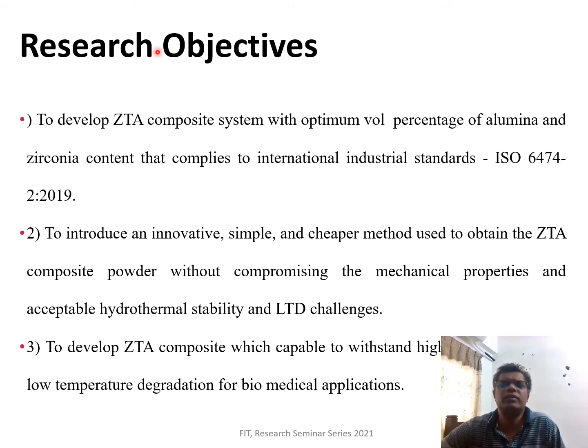So my research objective is to develop a ZTA composite system with optimum volume percentage of alumina and zirconia content that complies with the industrial standard ISO 6474-2:2019. Another objective is to introduce a more innovative, simple and cheaper method to obtain a ZTA composite without compromising the mechanical properties and acceptable low temperature degradation. And third, to develop a ZTA composite which is capable of withstanding a high low temperature degradation for biomedical applications.